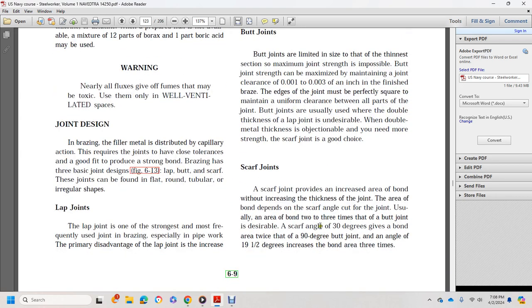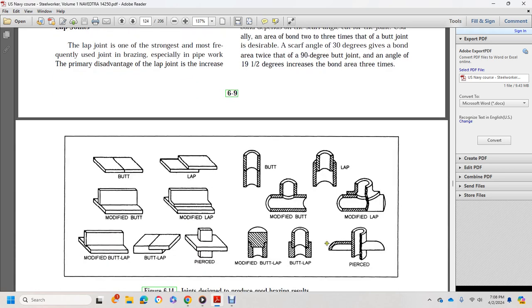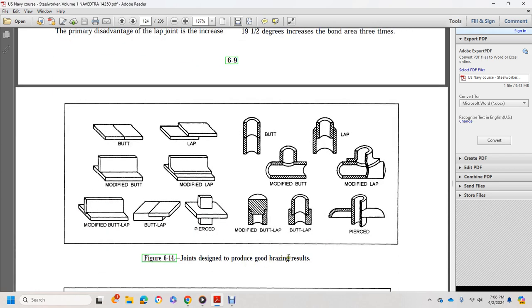Scarf joints provide an increased area of bond without increasing the thickness of the joint. The area of the bond depends on the scarf angle of the cut for the joint. Usually a bond area two or three times that of the butt joint is desirable. A scarf angle of 30 degrees gives a bond area twice that of the 90-degree butt joint, and an angle of 19.5 degrees increases the bond area three times. This shows joints designed to produce good brazing results.